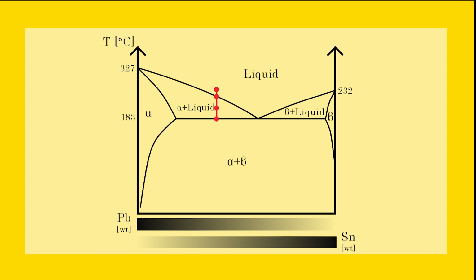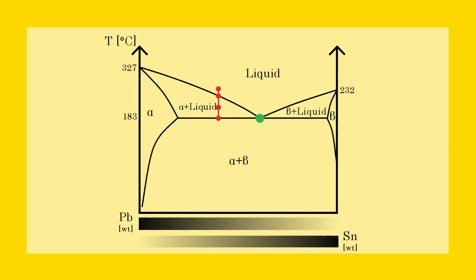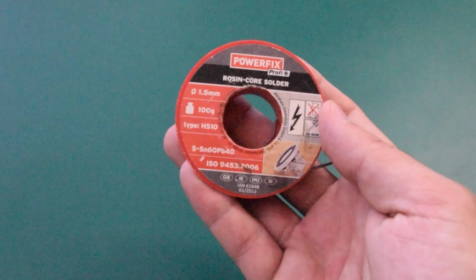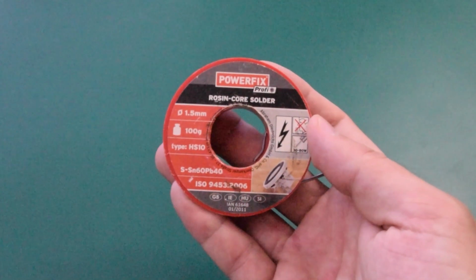How do we use this knowledge for soldering? Do you see that green dot on the screen? Our liquid will go instantly into solid without any granulation if we cool it through that point. It happens at 61.9% tin concentration, exactly at the bottom of the liquidus line, and that also indicates an ideal low melting point for our alloy, which is 183 degrees Celsius. This is why most leaded solders contain from 60 to 63% tin.